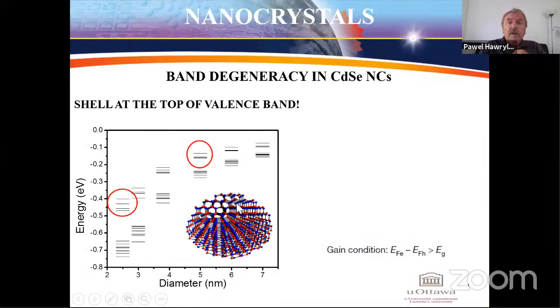So if you take a cadmium selenide nanocrystal as a function of its diameter and calculate the spectrum of the top of the valence band of this nanocrystal, then you see that the top of the valence band has a band of closely spaced levels. So it's not just an electron confined to a spherical potential. It has a band of states at the top of the valence band. So the hole created at the top of the valence band is spread around many levels, and so only a fraction of a hole can be assigned to the top of the valence band.